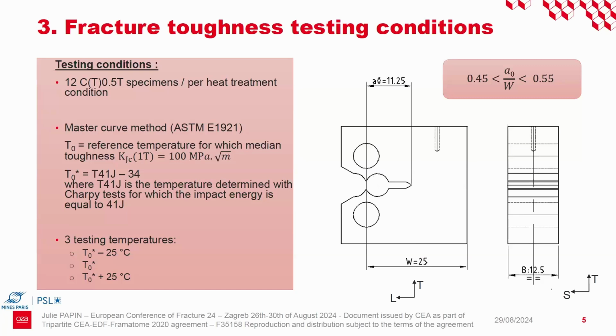This method allows to pre-estimate this reference temperature based on Charpy tests by using the temperature for which the impact energy is equal to 41 joules. Based on this estimated temperature, we define 3 testing temperatures, which are T0 plus and minus 25 degrees.